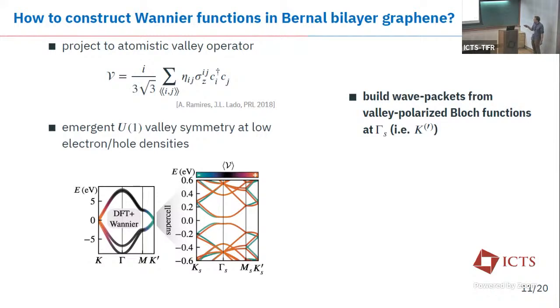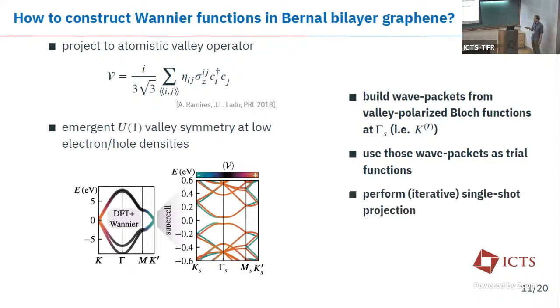We take valley polarized Bloch functions from there, and we build wave packets from those Bloch functions. We transform them to real space, set up a Gaussian that goes across this real space wave packet, and then use those wave packets as trial functions for the Wannierization. There are some technical details that can be discussed on a personal level, I think this is not suitable for the talk, but there is some iterative, single-shot-like projection procedure to localize them even further and have a very local and well-localized basis.